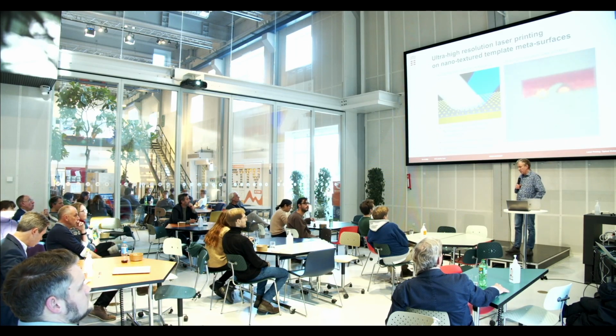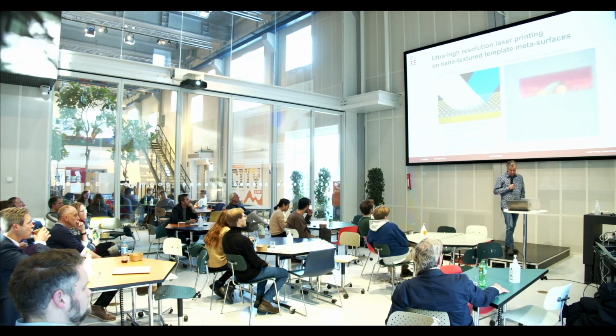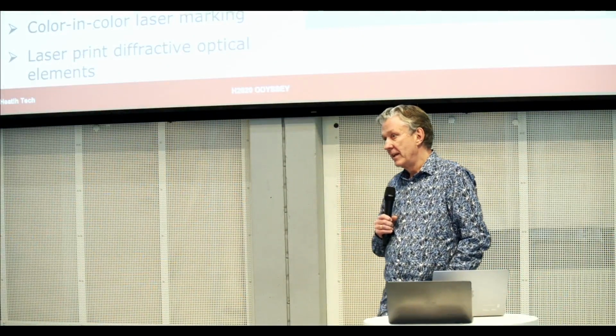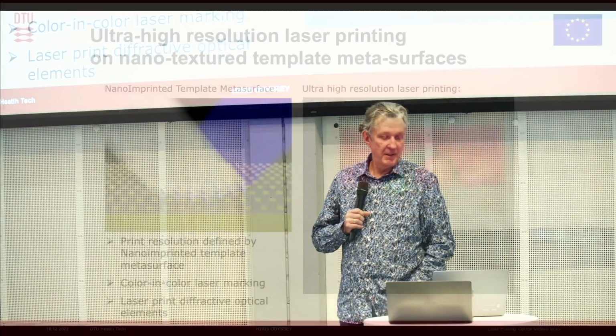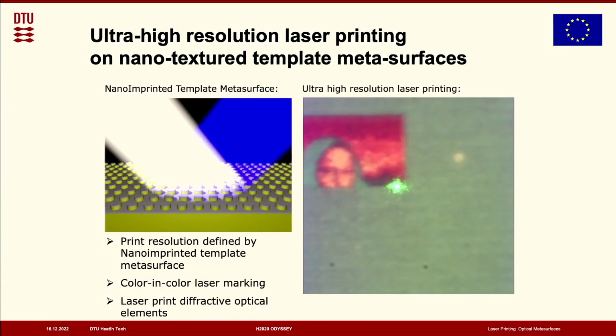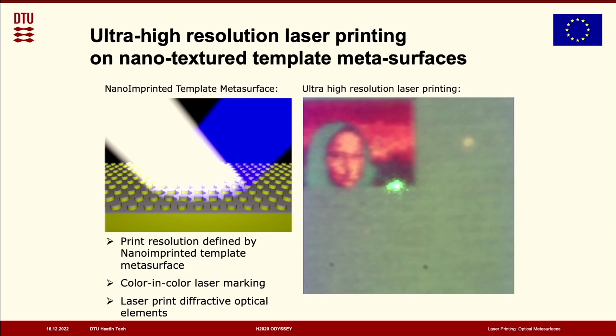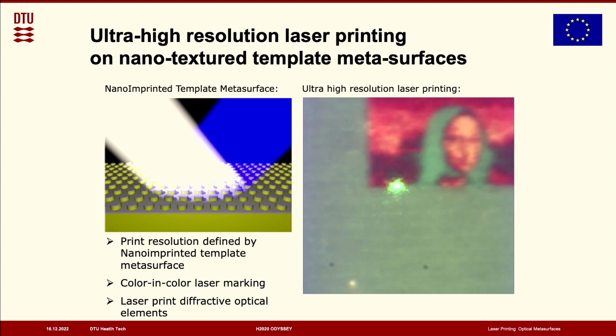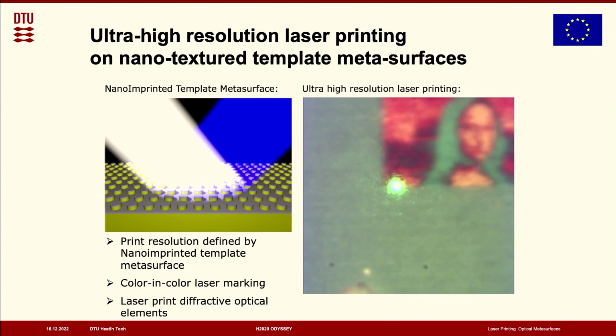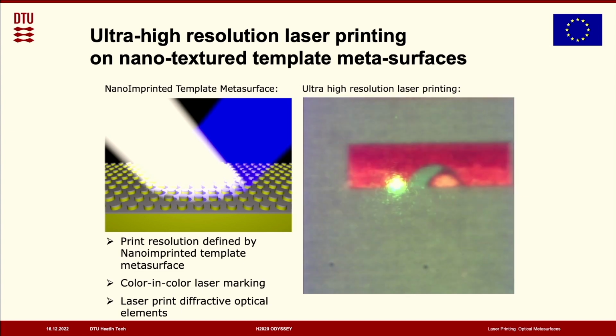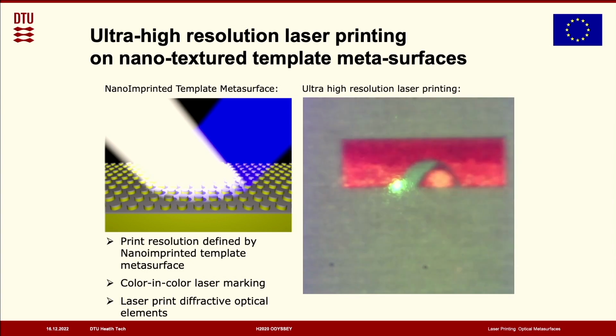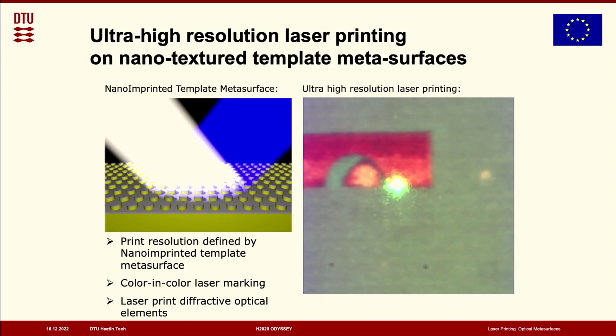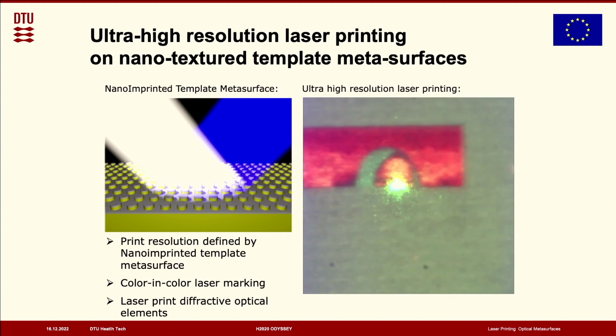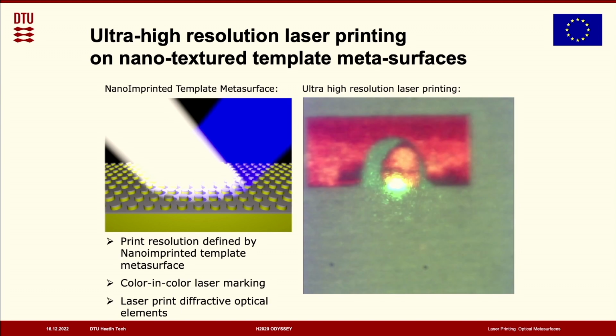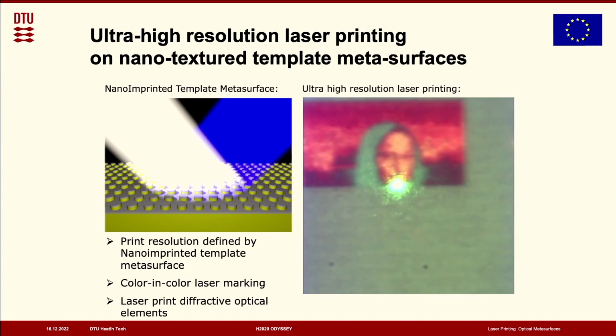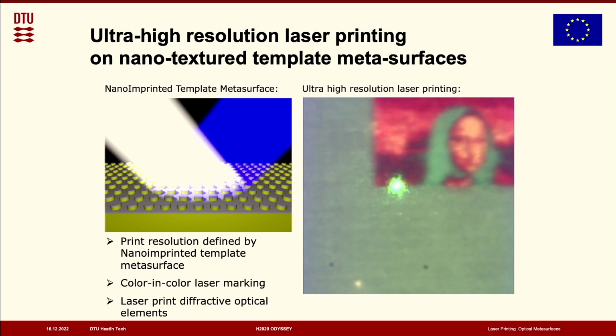So these kind of so-called structural colors or ink-free colors, they rely on that the material absorbs the light at this optical resonance, and we made some research and discovered that you can actually also exploit this absorption resonance in these nano meta-atoms by taking a laser which also has the same wavelength in resonance with these meta-atoms. So in this case, we took a green laser, and the green light is absorbed by this apparently blue surface.